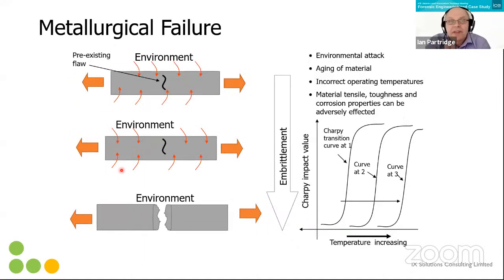Another way it could fail is metallurgically. Now, this is generally the hardest to predict. It tends to be the hardest to inspect for. But what you get is the environment attacking your material. Now, this can create a crack. It can age the material. It can embrittle the material, so reduce its toughness. It could reduce the corrosion resistance of the material, or it could change the tensile properties. Probably the most common that we see is it reducing the toughness of the material. So